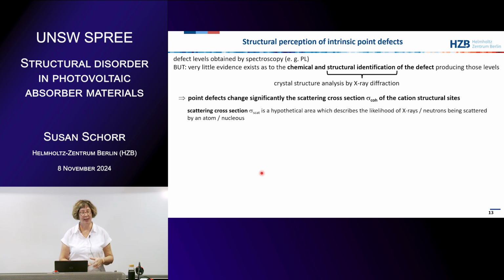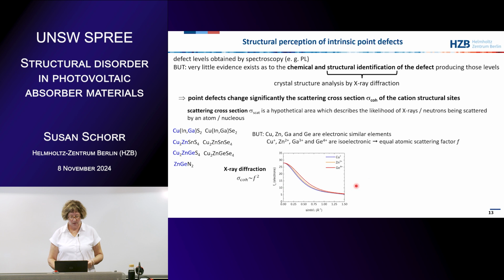Why can we do that? If we have enough defects, so if the concentration is high enough, and I mean it should be more than 10 to the 18 per cubic centimeter, which is a lot of defects, then the point defect will change the scattering cross-section of the structural site. This means the cross-section on which the X-rays or the neutrons are being scattered. So this describes the likelihood of scattering on a structural site where normally an atom is sitting. Here I show you the atomic scattering factor for copper plus, zinc 2 plus, and germanium 4 plus, and you will see it's very similar. And this is in principle the scattering power of these ions if you use X-ray diffraction.